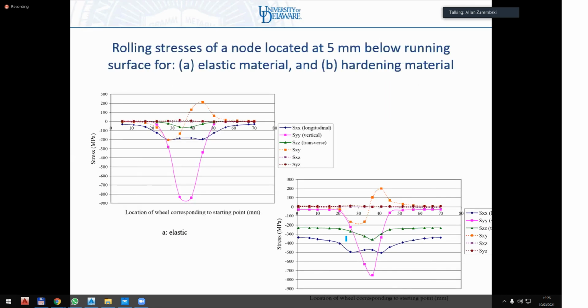And just to give you an example, this comes out of some finite element modeling of the rail. These are my stresses in the various orientations. First of all, this is the rail stress 5 millimeters below the running surface of the rail for an elastic material, before any work hardening or plastic hardening. Just below the running surface the contact stresses are very dominant. My vertical stress is this purple, my longitudinal stress is this horizontal, my transverse stress is the green, and these are my 3 shear stresses.